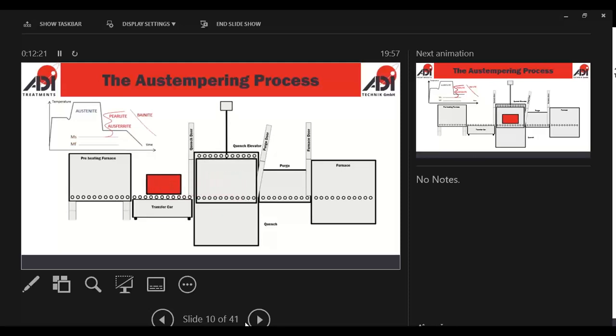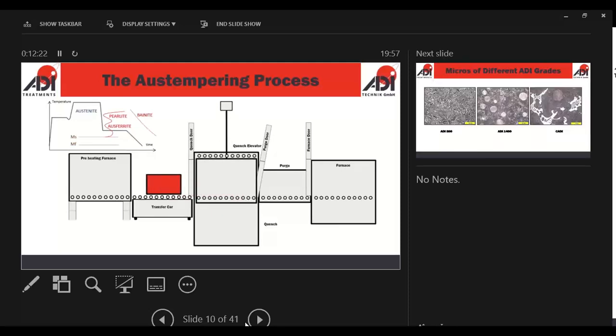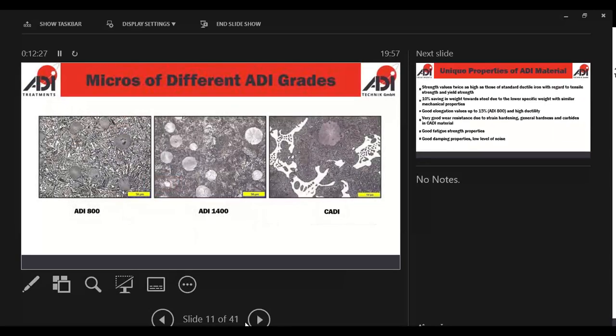Once the castings have gone through that process, we take them out and obviously we wash off the salt. If everything's done correctly, we will end up with a lovely looking austempered microstructure. On the left-hand side, we have one of the lower grades of austempered ADI, which is an ADI 800. This is a coarse microstructure consisting of ferrite platelets and high carbon stabilized austenite.